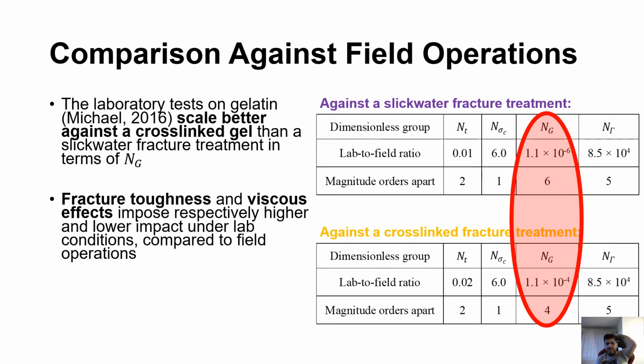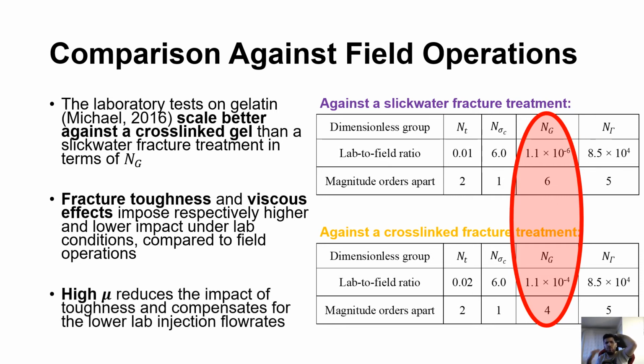We see that the fracture toughness imposes a higher impact under laboratory conditions than field operations, and viscous effects impose lower impact under laboratory conditions and higher impact compared to field operations. This implies that if we use a higher fracturing fluid viscosity in the laboratory, we are able to reduce the impact of fracture toughness and compensate for the lower laboratory injection flow rates.